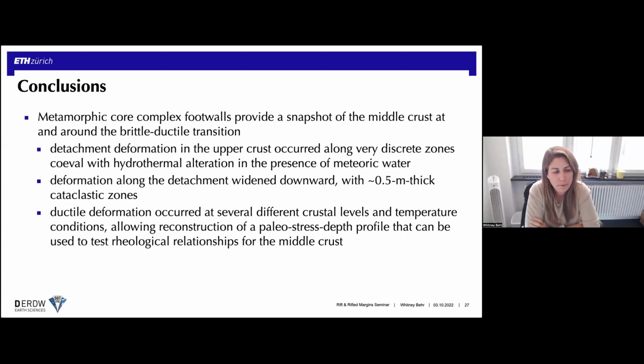So the Whipple fault in particular has about 40 kilometers of displacement based on an offset dike swarm. And the timescales, it's tricky whether you relate the timing of extension preserved in the mylonites with slip on the active detachment, because I mentioned that we interpret the early phases of deformation, including incipient ductile deformation, as the detachment is developing. But if you do that, it's about 15 million years. But Danny will probably talk in more detail, including about the Whipples, about the time constraints. But that's what it appears to have accommodated. From about 32 to about 15 or 16 Ma is the age range that seems to show up for the Whipple fault in particular.